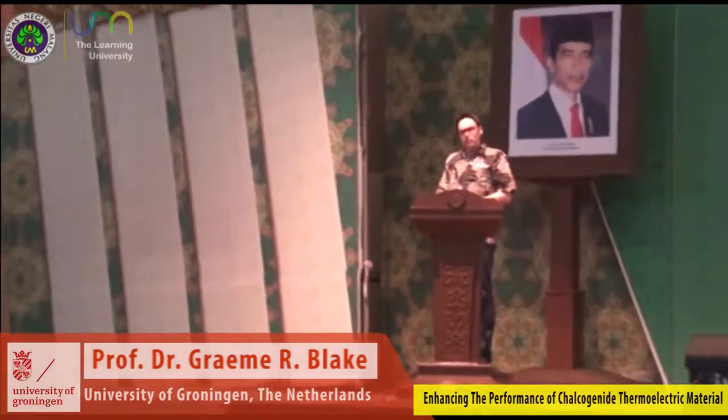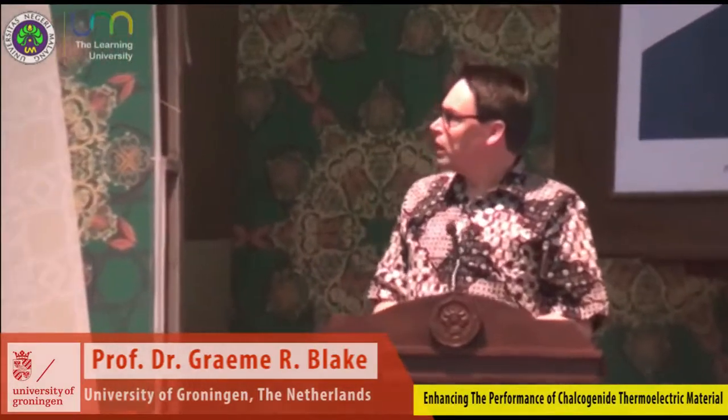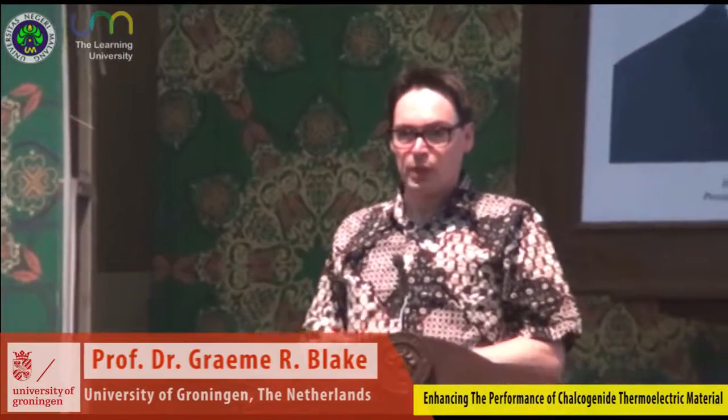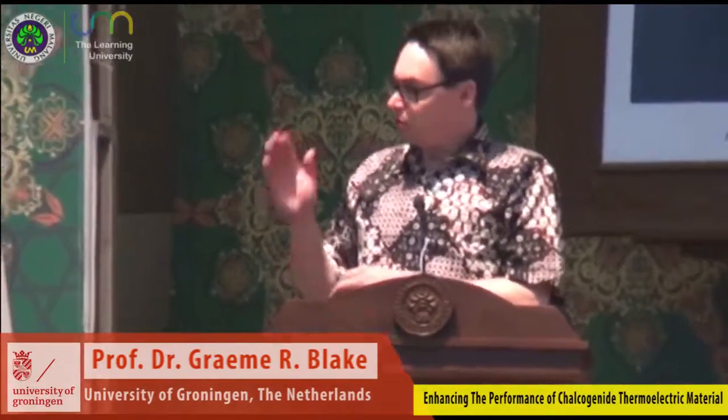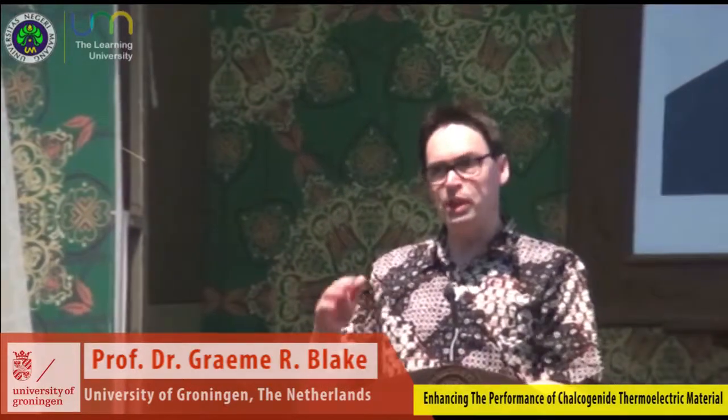I should mention that there are a lot of errors involved in these measurements, and the typical error bar on the measurement of kappa is something like 10 or 20%. So you should be careful when you see these results in the scientific literature. Usually people report these values as if they're exact, but they're not really. You should always bear in mind that there's a very large error bar in this. Next, please.